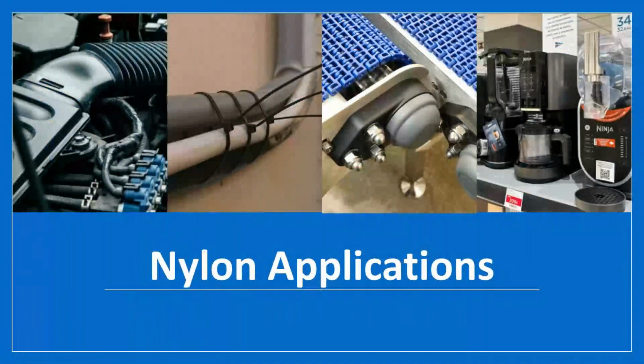Some applications - a very wide range because we have a broad range of nylons we've been talking about. Stuff like your under the hood applications, radiator end tanks, are going to be nylon materials typically. Zip ties are generally nylon based. Modular belting - again, resin on resin wear is much better with nylon than acetal, so a lot of plastic modular belting could be some sort of nylon. Gears, like some of your blenders or creamers, if they're running quickly and have to wear really well, a lot of times they'll use something like a 4-6 for high speed, high pressure, or even slightly high temperature. If it's running really fast and temperatures get high, you might use a 4-6 for gears. You could use a 6-6 for gears as well, and even some housings could also be nylon. So a lot of options for nylon applications.